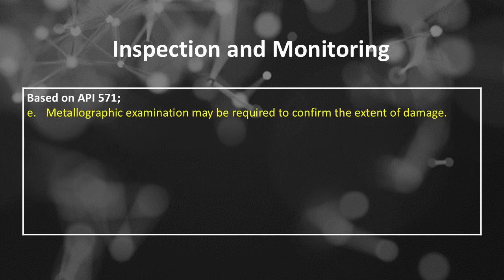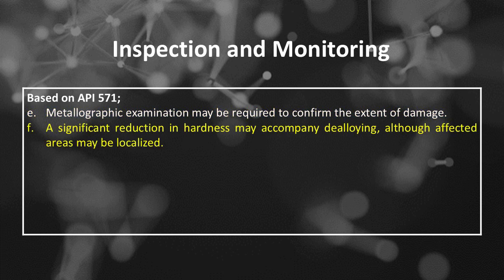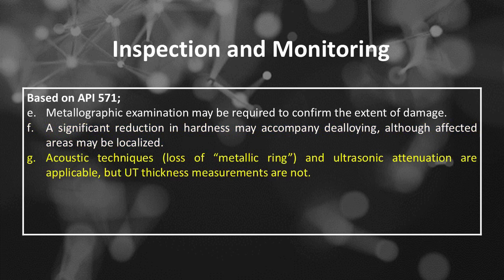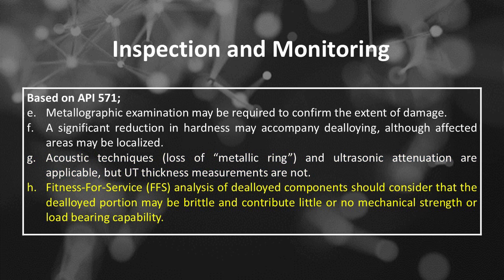E. Metallographic examination may be required to confirm the extent of damage. F. A significant reduction in hardness may accompany dealloying, although affected areas may be localized. G. Acoustic techniques, loss of metallic ring, and ultrasonic attenuation are applicable, but UT thickness measurements are not. H. Fitness for service, FFS, analysis of dealloyed components should consider that the dealloyed portion may be brittle and contribute little or no mechanical strength or load-bearing capability.